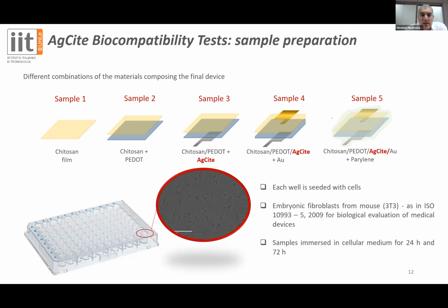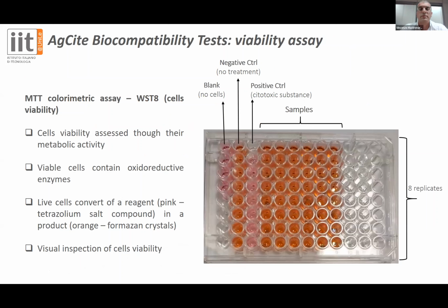So we tested the biocompatibility also of the silver ink by preparing different samples, in this case 5 samples, including all the materials used for the sensor. We performed this biocompatibility test in order to assess the metabolic activity of the cells in cellular medium when we put inside also our fabricated samples, and some tests of absorbance of the cellular medium. The metabolic activity of the cells has been tested by a colorimetric assay, MTT, and we put our samples inside a series of wells containing the cellular medium, the cells, and a reagent that is the tetrazolium salt compound.